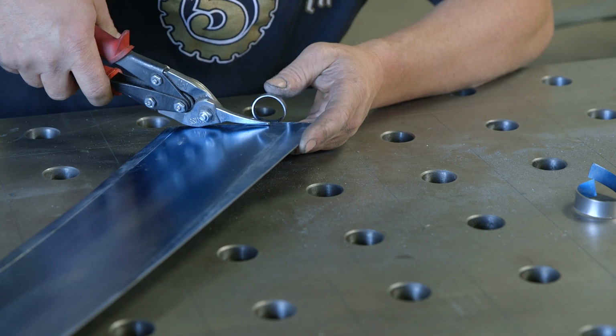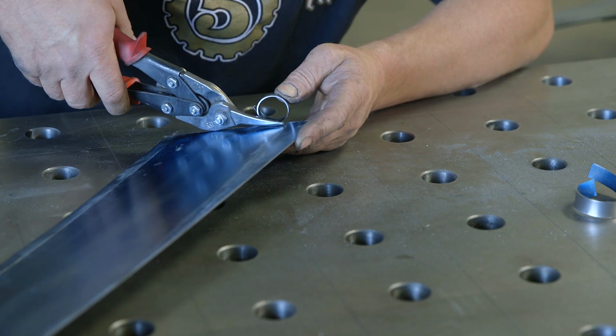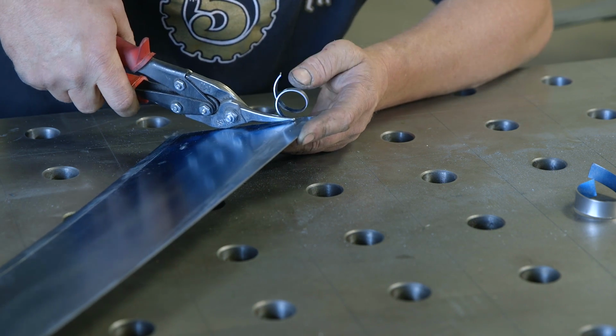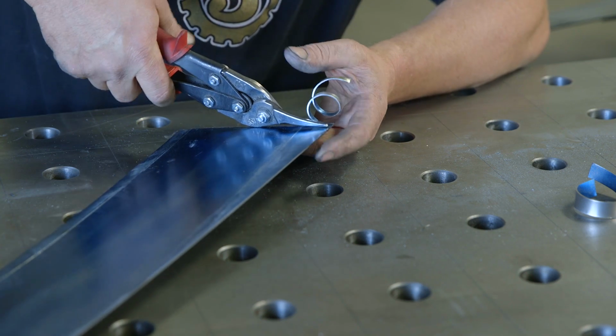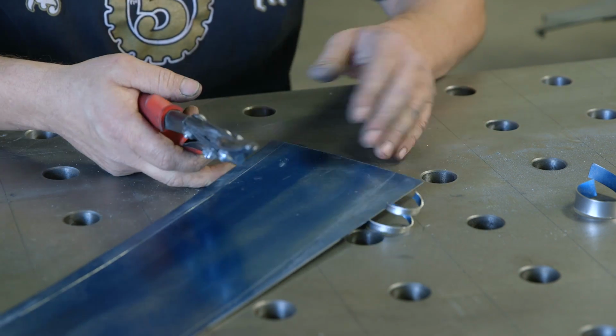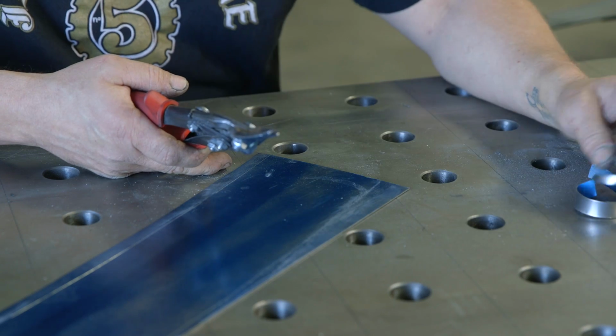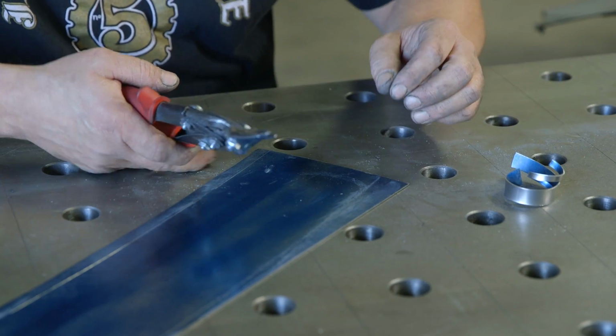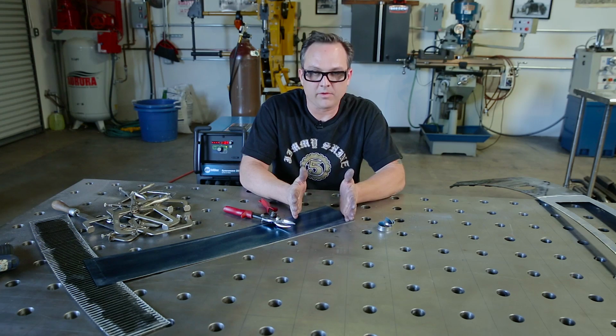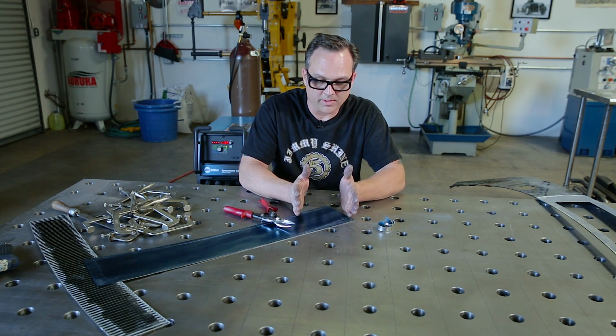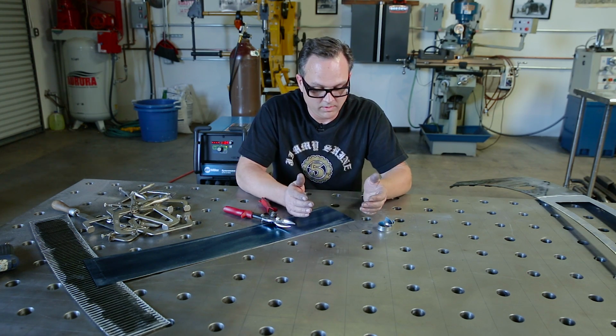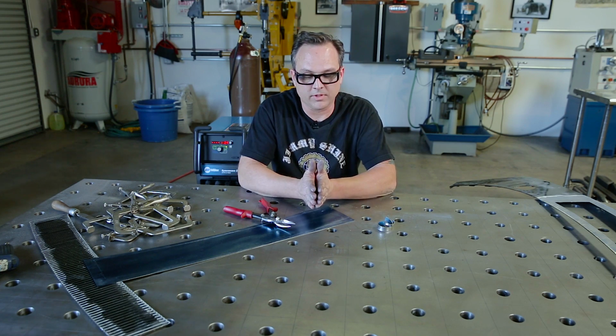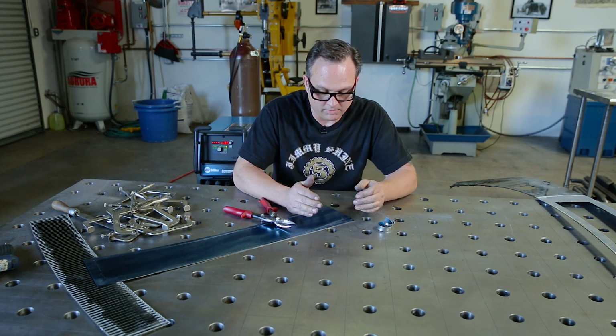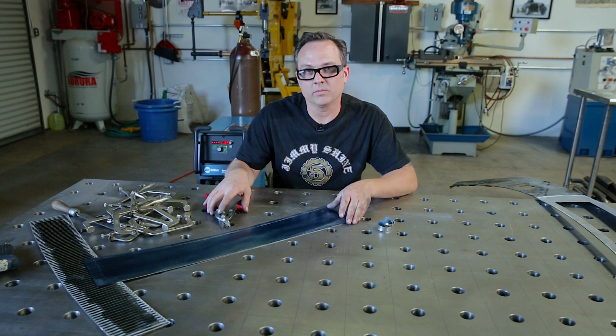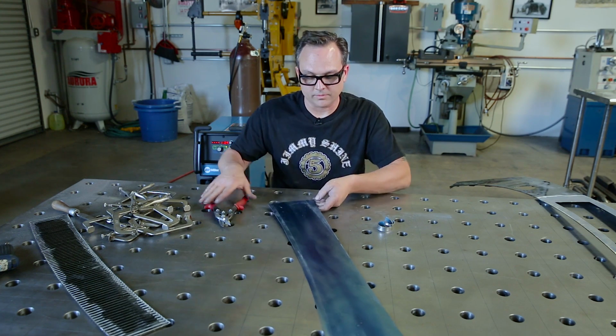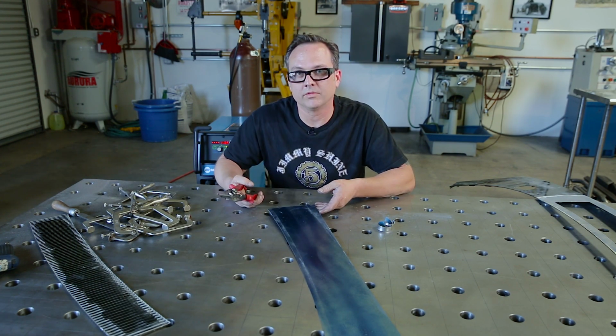And I'll tell you about it in the end, but when I make the final welds, it really helps prevent warpage by having these cuts as straight as you can and close as you can, because the fit's so tight that you don't have a lot of filler metal going in. Because you think about it, the wider the gap, the more filler metal, that's more that it can contract. The tighter the fit, there's less for it to contract. And that really makes a difference on doing finished sheet metal. So now I'll go around the rest of the piece and finish up.